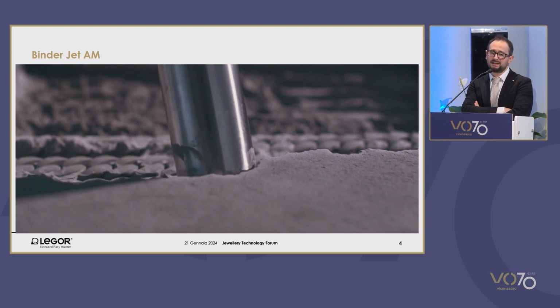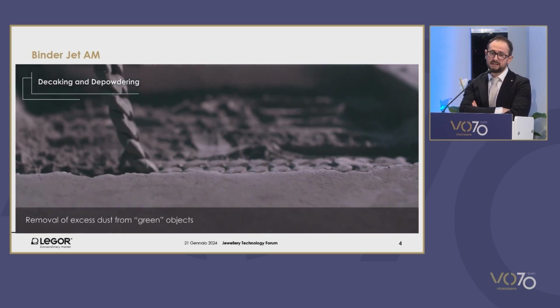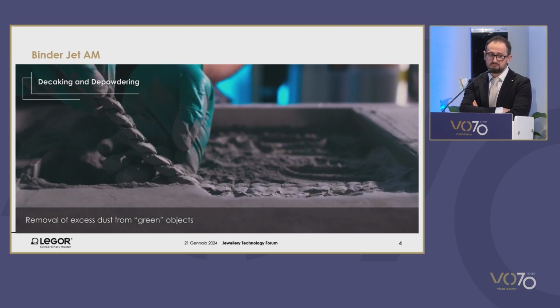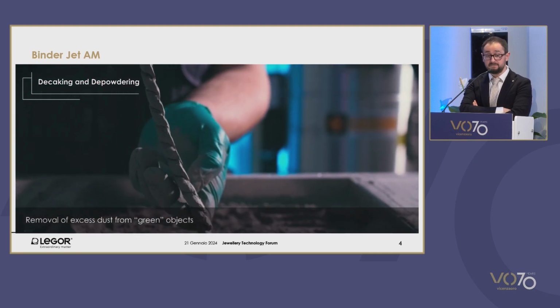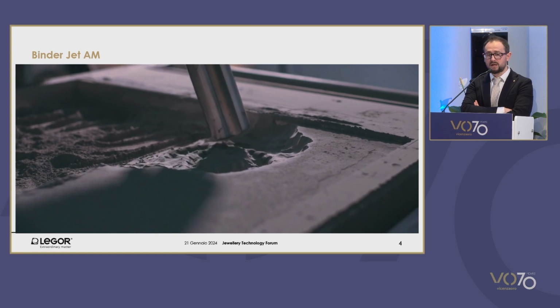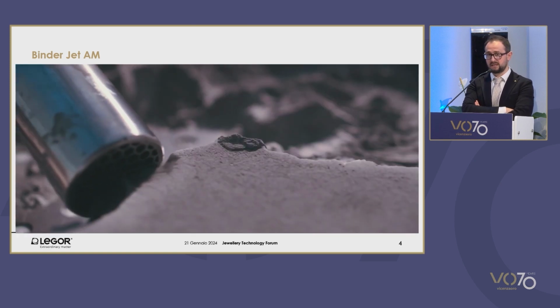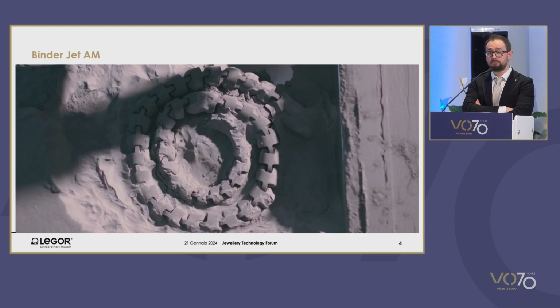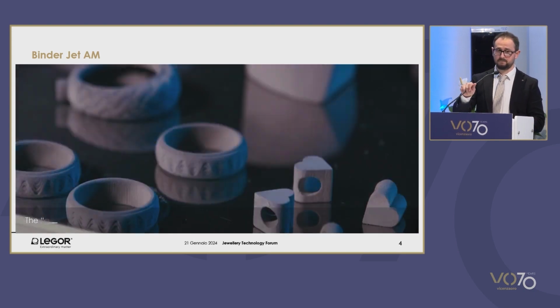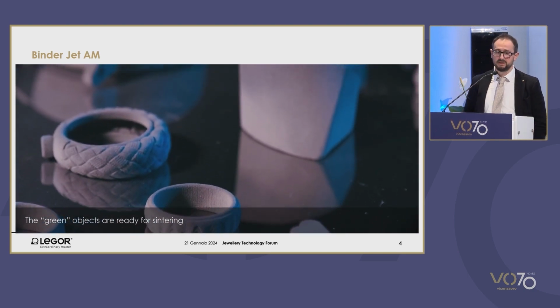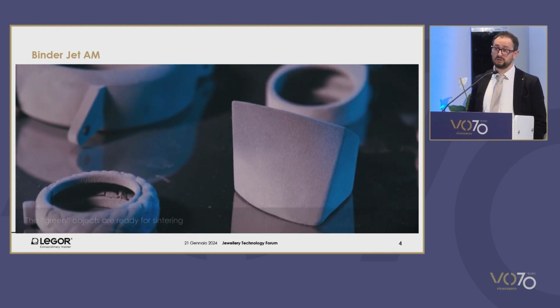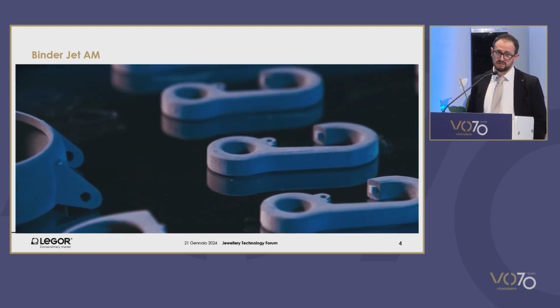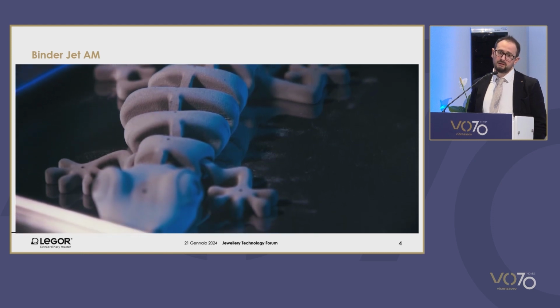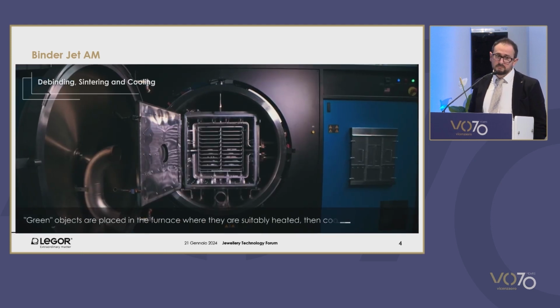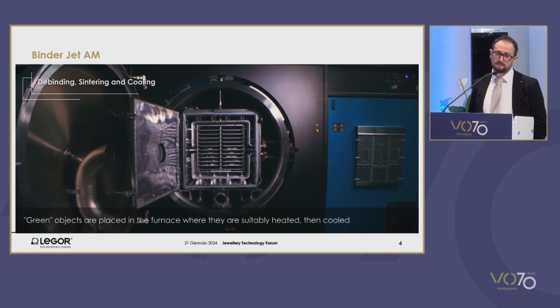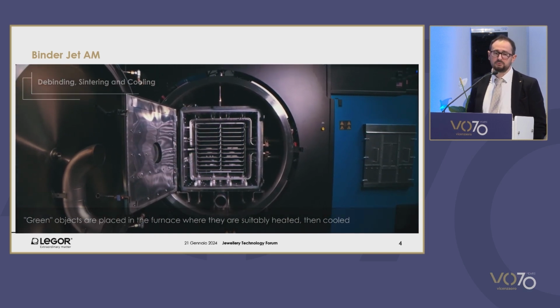That is, the binder has to be treated to guarantee mechanical resistance. And then the pieces are extracted at the moment manually. After having been cured, they are sufficiently resistant to be manipulated. They're placed on trays and are then submitted to heat treatment to achieve the sintering process. The item is now ready to be placed in the oven.